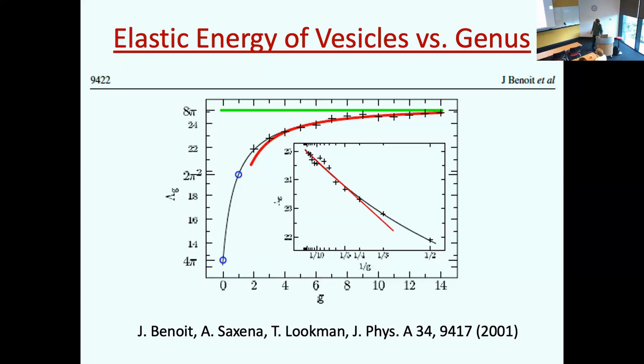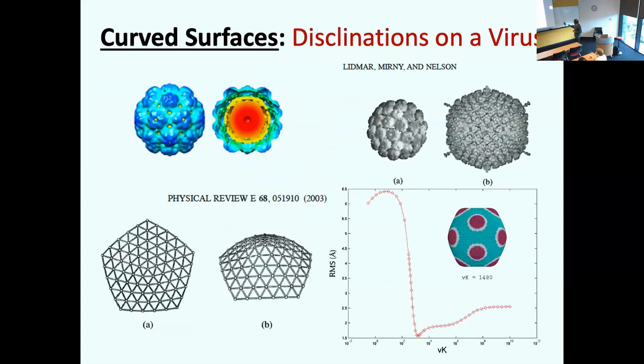There are certain viruses. This is a very nice paper from David Nelson. And so there are certain viruses which have this kind of topography. And they have a lot of, I'm not showing all the details, many disclinations, 5-fold disclinations. So if you take a triangular net and create a disclination, it will bend, curve like this. And by doing this and using the Helfrich free energy that I showed you in the previous, they were able to do some MD simulations and also look at where these buckling happen and what kind of disclinations happen in this. I'm just giving you an example, and this is the von Karman number. So if you're looking at your calculation versus actual observation, for what von Karman number you'll get the optimal structure, etc. Just to give an example.